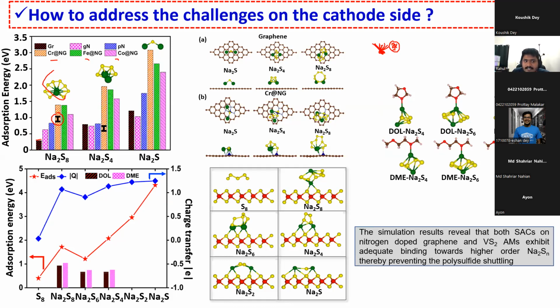Now, when we use the single atom based catalyst, you can see that the interaction energy is significantly improved, and it is very high when compared to the interaction energy with the electrolyte. So it will bind the polysulfides within the electrode rather than sending them to the electrolyte. Then you can ask, what's the reason why graphene is not binding the polysulfide? The reason is that you can see clearly there is no bond formation in all these polysulfides. That means there is just a weak physical van der Waals interaction between the polysulfide and the graphene, which is holding them together. There is no chemical bond formation, so there is no stronger chemical interaction between these two systems.